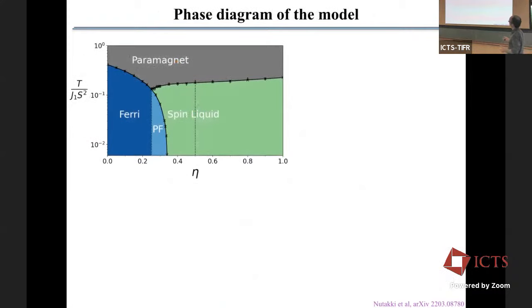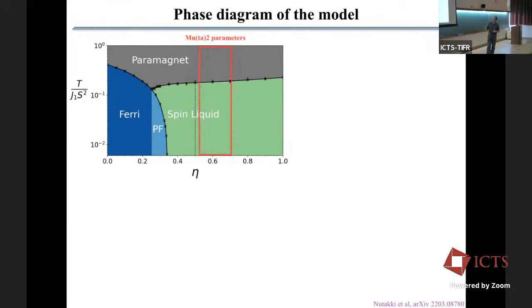And so if we use classical Monte Carlo to study the phase diagram of the system, I'm going to detail it in a moment, but we see that there is a broad spin liquid region here. The manganese parameters are all in this region. So that's a good thing, that even if we have uncertainty about the precise value of these parameters, J1 over J2, we know that they all fit right in the middle of the spin liquid region.